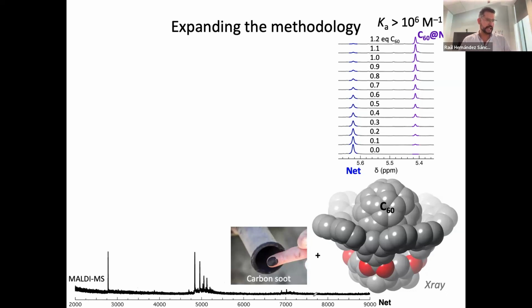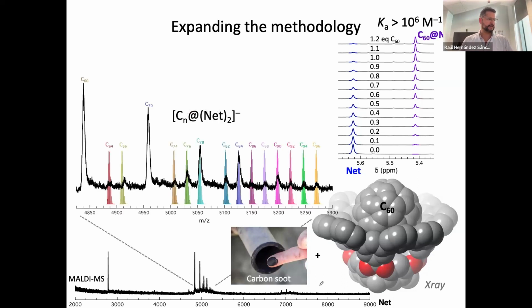And so this is the mass spectrum that you obtain, right? This spectrum goes from 2000 to 9000, and essentially you only see a few peaks, right? And if we center in this region of the spectra, we can see that this particular net is essentially sequestering all of the different fullerenes from C60 all the way up to C96 in one go, right? This is pretty remarkable because you have one host being selective towards fullerenes, because you can imagine, right? This is carbon that has everything that you can imagine under the roof, right?